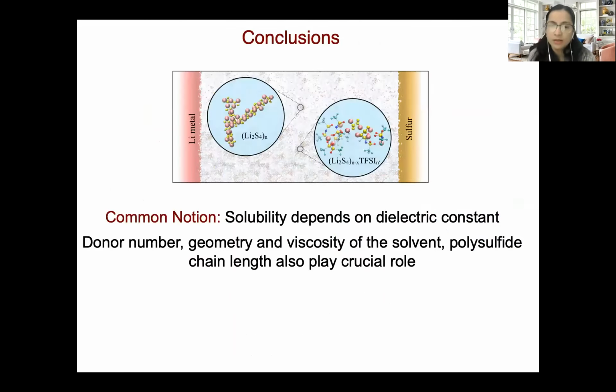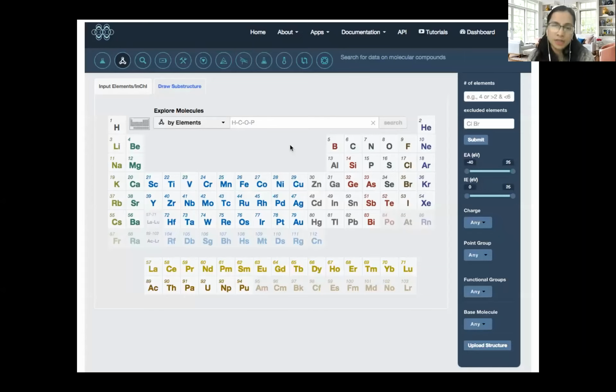Okay. So for lithium sulfur batteries, we identified a lot of different descriptors, several parameters, such as the donor number and the geometry of the molecules and the viscosity of the solvent, which affects the structural and dynamical properties, which in turn affects the redox shuttle phenomenon. And some of the DFT results that I presented today are available on the Electrolyte Genome website. If you have never heard of it, I would suggest you go and check it out.